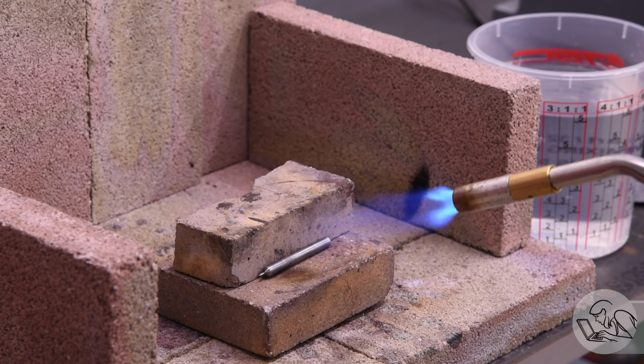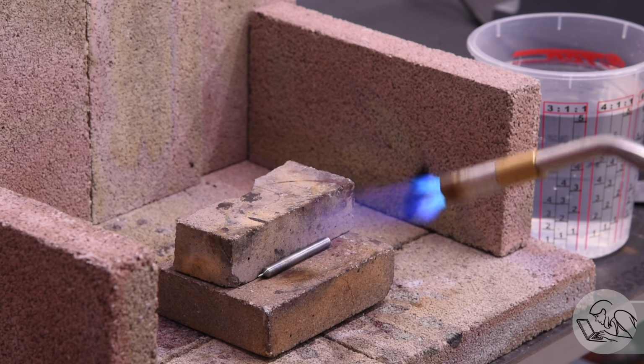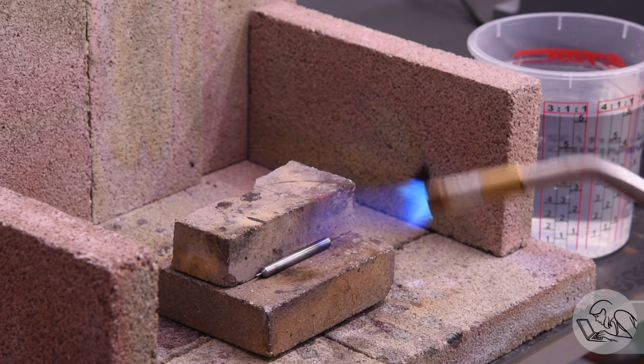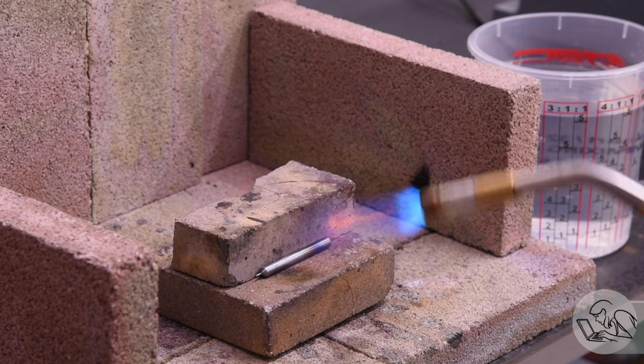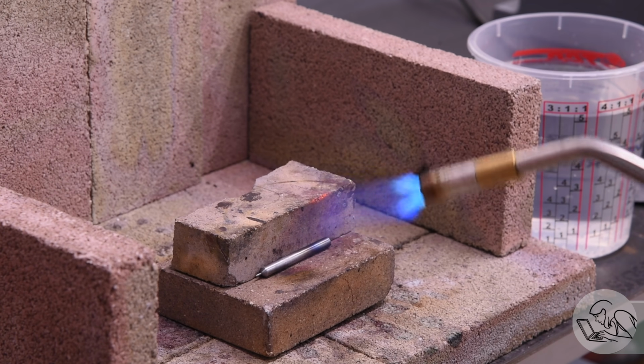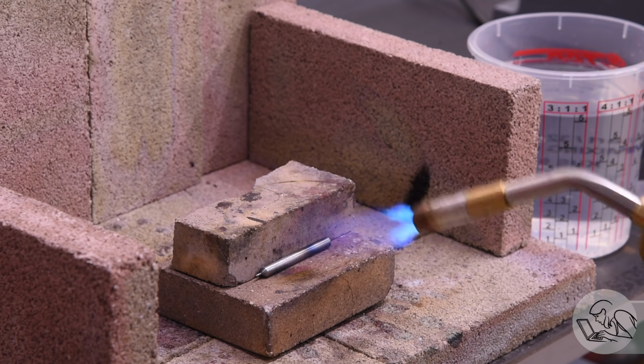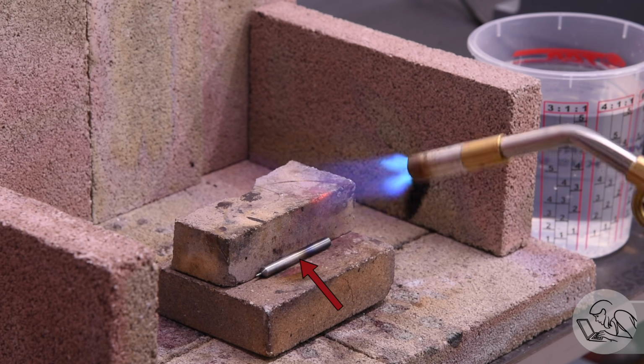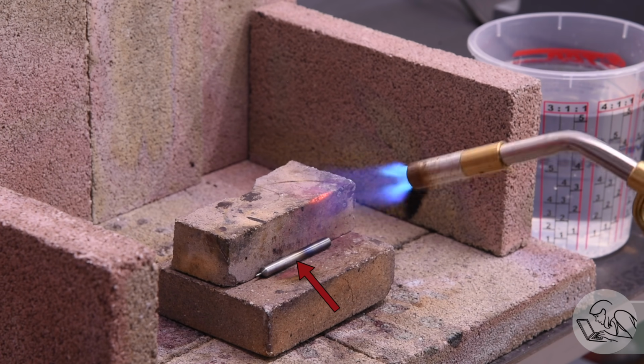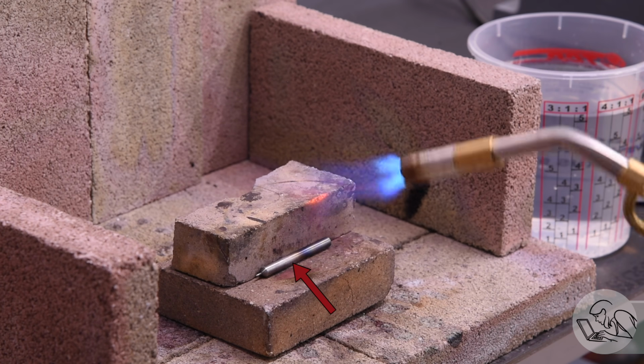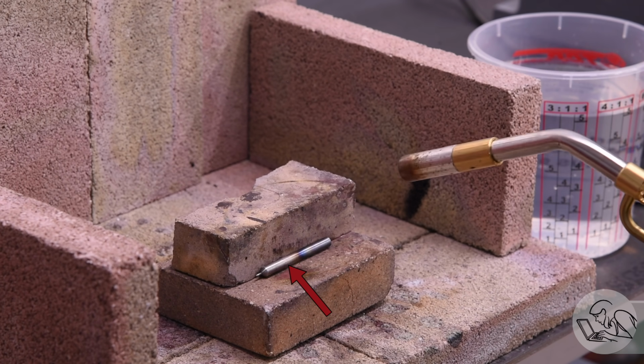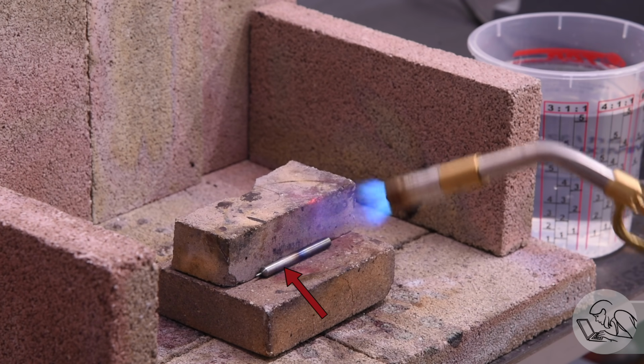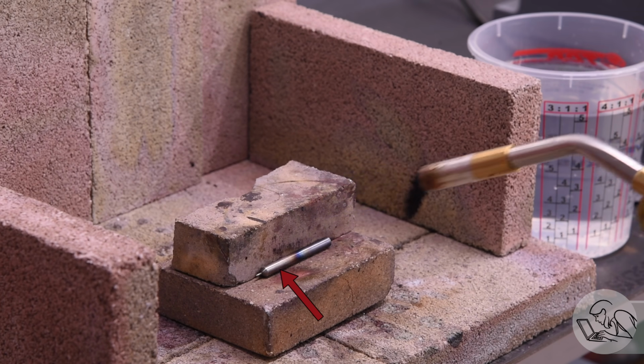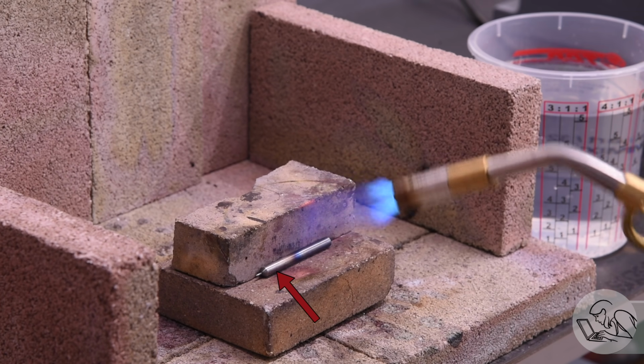To temper the piece, I heat it from the far end, not the business end of the tool, but the far end, and I do this very carefully and slowly, not too much heat. You don't need very much for this step. And I'm watching the color creep down the end of the tool. You'll see a yellow and then a brown, then a blue and a purple. And you want to stop when that yellow color, as it creeps down the end of the tool, just reaches the tip of the tool.